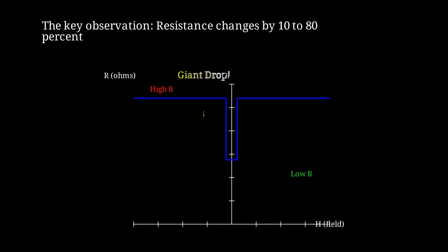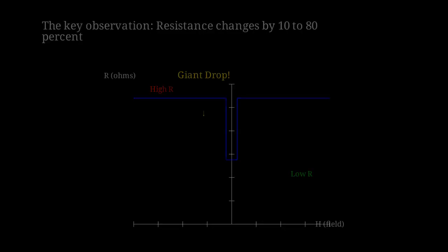This is a typical GMR curve. At zero field or low fields, the resistance is high. This corresponds to antiparallel alignment of magnetic layers. As the field increases beyond a critical value, the resistance drops sharply to a low value. This corresponds to parallel alignment. The resistance change can exceed 50% in optimized structures.